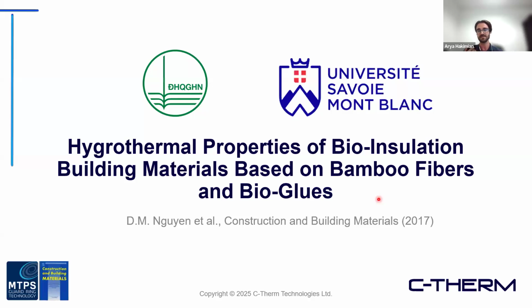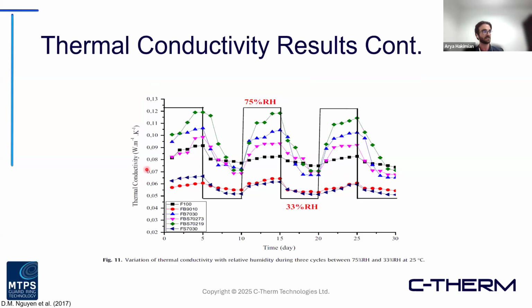Kind of following up on that, this is an example of a publication. It's one I like to show when we're talking about insulative materials in general. Now, it's not on a traditional aerogel, and it's actually just a bio-based standard insulation, but it's a really nice data set that I wanted to highlight. This was some work out of Vietnam and France. And as we can see, again moving on that idea of moisture content, with some of these bio-based insulations, increasing the relative humidity, you see a net increase in thermal conductivity, which in this context is something we are trying to avoid. We want it to have the lowest value possible.